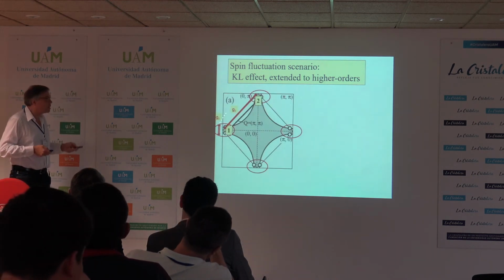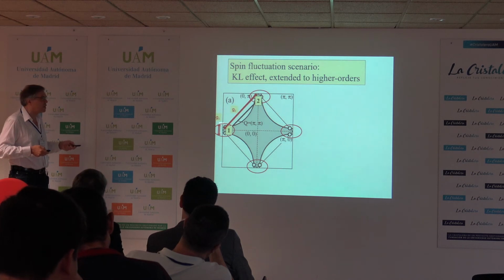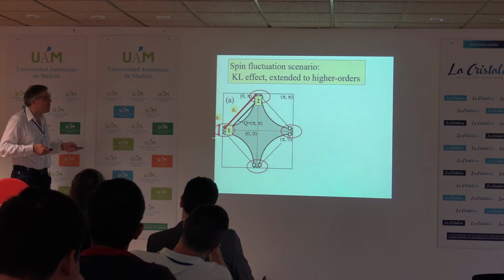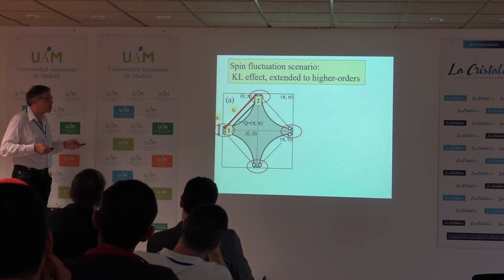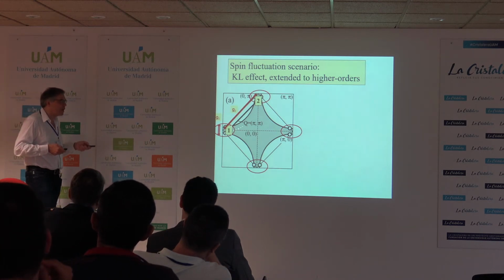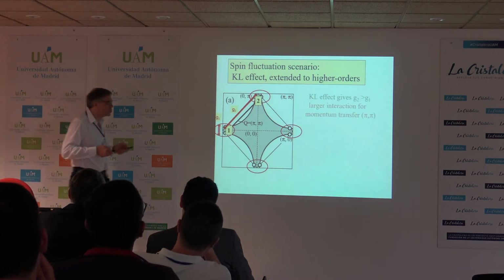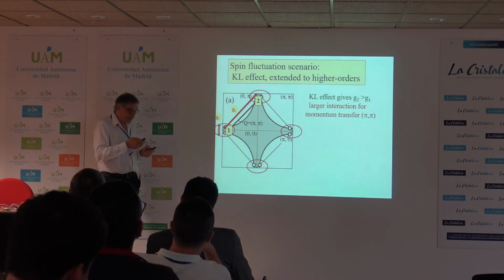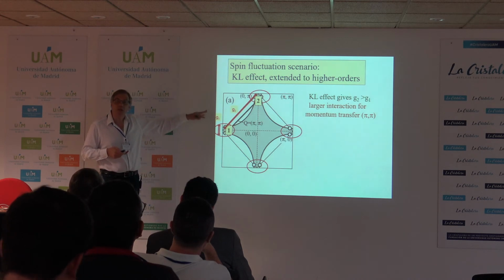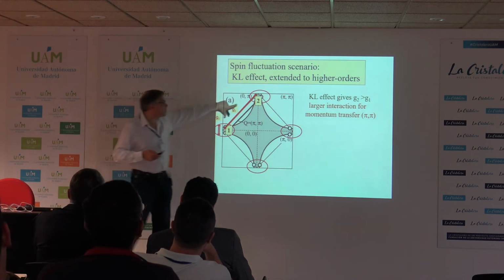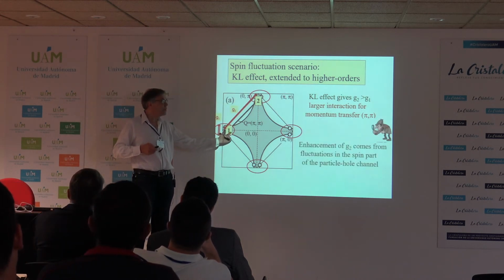Going back to cuprates, remember the story. The story is that we started with the case when G1 and G2 were the same, and we obtained that G2 becomes larger than G1. Now I want to consider what happens if originally G1 was larger than G2. But that story, the Kohn-Luttinger story, basically tells you that this interaction gets larger than this one.